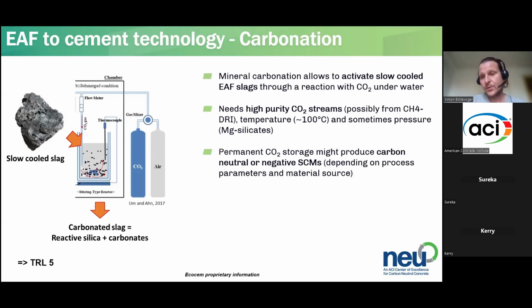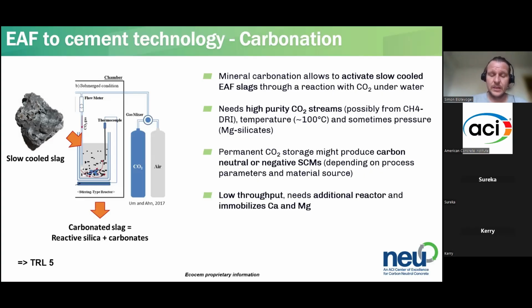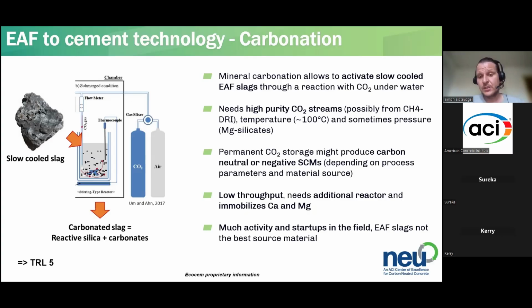Those techniques would also allow permanent CO2 storage and produce a carbon neutral or at best negative SCMs, which depend a bit on your process and the material source. The problem is, again, scalability. You need an additional reactor. You would need to dry the material afterwards, and it's rather fine material. So this may be a bit slow. And one point is also that in SCMs, it's rather rare to find a decarbonated source of calcium and magnesium. And here you would immobilize the calcium and magnesium that were decarbonized in the steelmaking process, though there's a bit of a trade-off.